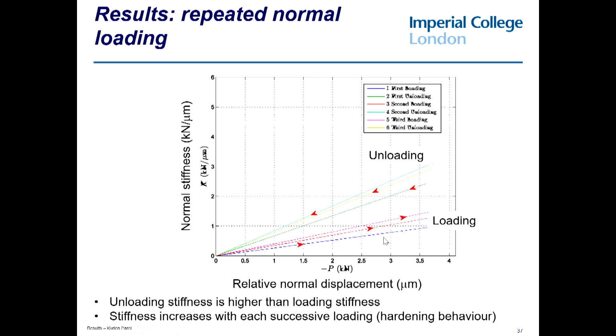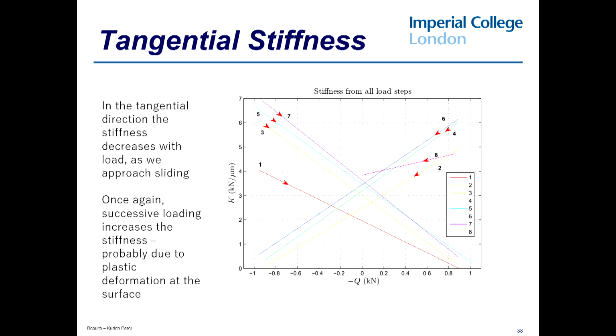So you can see here we've done loading and unloading of a normal contact, and the contact changes, its response changes each cycle of loading. And almost certainly that's because the geometry is changing. And the same thing kind of happens when we try and slide contacts. So you can see here that here's the stiffness.